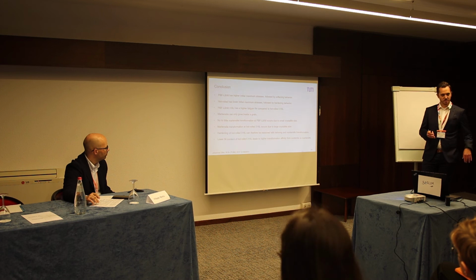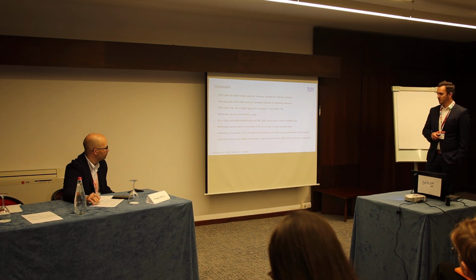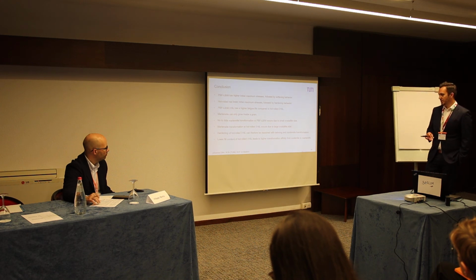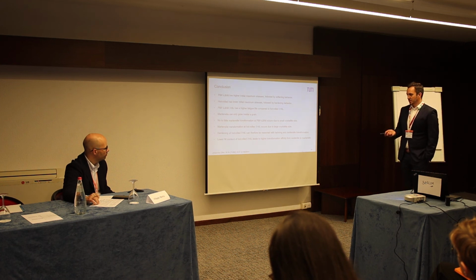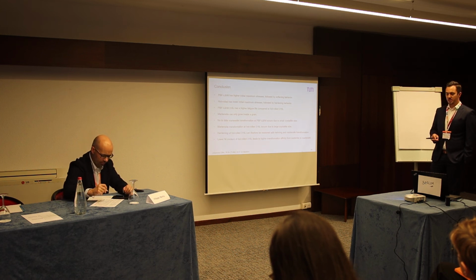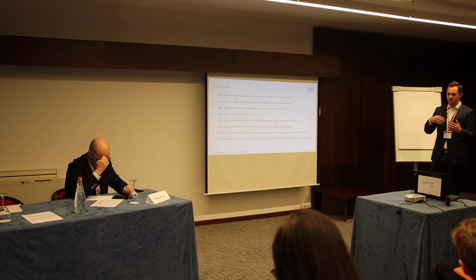So we probably maybe have twinning-induced plasticity at the 2.5% strain amplitude. However, we could see the martensite transformation at the hot roll 316L due to the larger crystallite size, and therefore the effect might be a bit bigger. So therefore we can say that hardening of the hot roll 316L can be reasoned with twinning and martensite transformation, so it should be a mixture of it. But in the end, also the lower nickel content of the hot roll 316L may lead to a higher transformation affinity from austenite to martensite. If you take a look at the Schaeffler diagram, you can see that with a lower nickel content, we're moving closer to the austenite and martensite area.